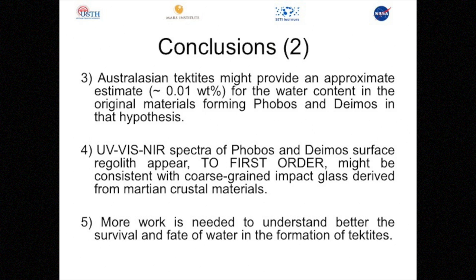And the final one: when we compare the spectra of Phobos and Deimos surface regoliths with the spectra of tektite, it appears that, to first order, they might be consistent with coarse-grained impact glass derived from Martian crustal material. All of this is just preliminary work, and we need to do more to better understand the survival of water in the formation of tektite.